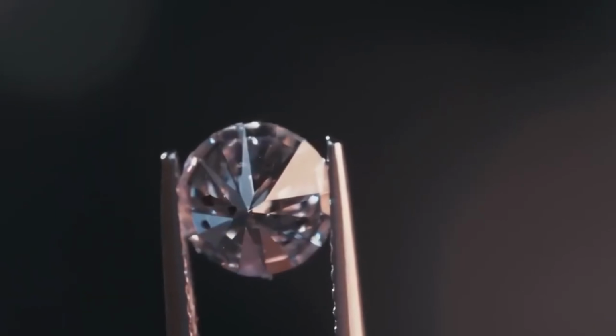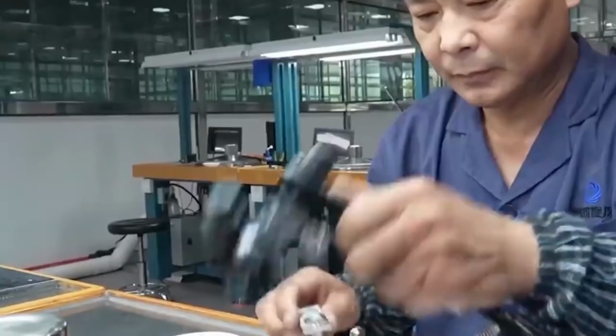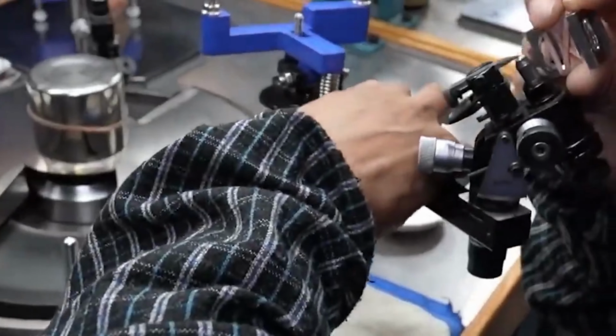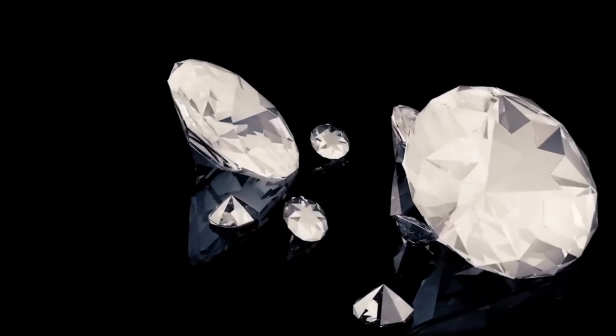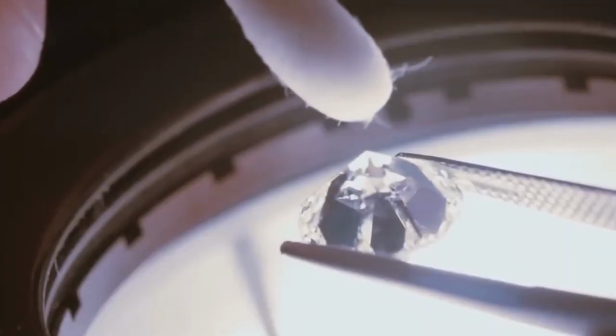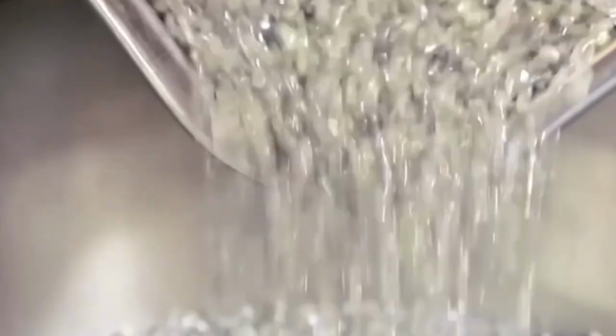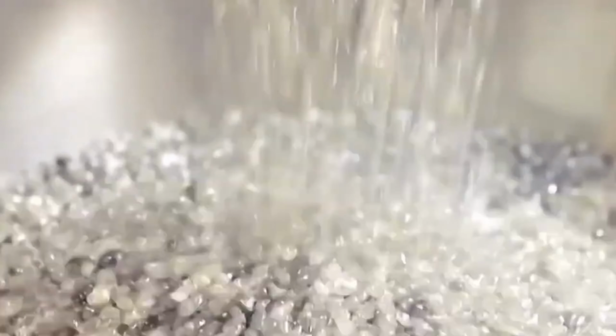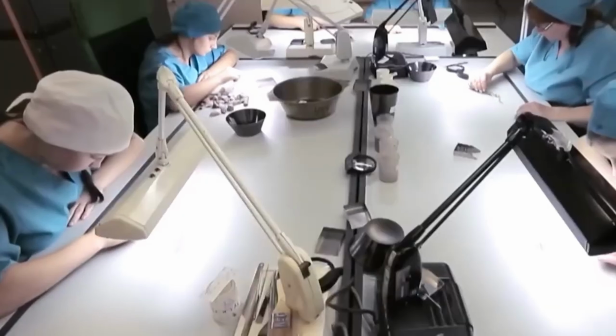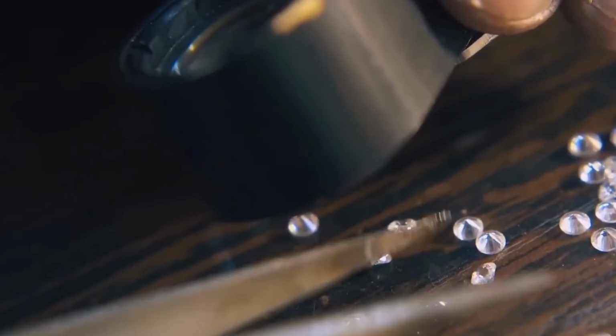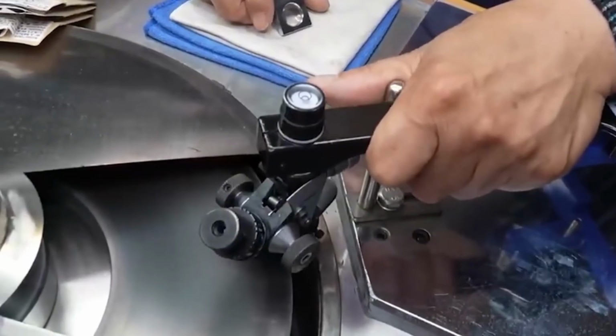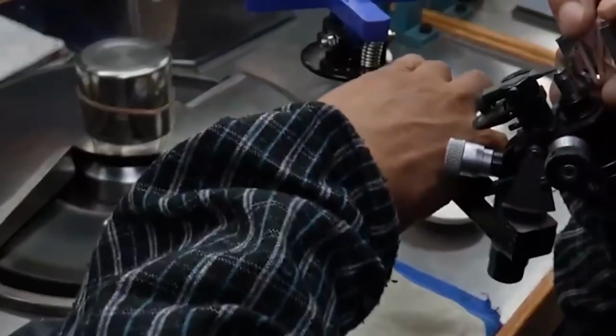Once faceting is complete, polishing begins. Polishing refines each facet to a mirror-like surface. During polishing, technicians adjust the diamond's angle, pressure, and positioning with exquisite control. Even the slightest vibration can leave faint polishing marks known as burns, or microscopic lines that reduce brilliance. State-of-the-art polishing labs use vibration-isolated tables and laser-aligned arms to achieve perfect finishes. The goal is total symmetry. Each facet should mirror its opposite side with ideal proportions.